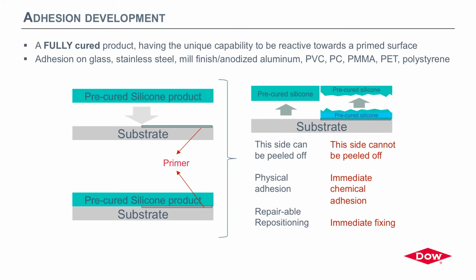So we have here a fully cured product that is transparent and that has the unique capacity to be bonded after cure on the substrate. And it is quite robust in adhesion, even if there is no filler. We have performed adhesion tests and verified that we can develop post-cure adhesion to metals, copper, aluminum, different types of finish, all kinds of plastics, and of course glass, stainless steel, and so on. And the trick is actually to use a primer.